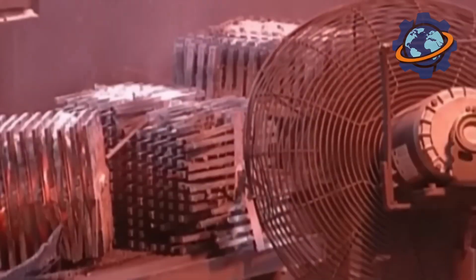Contact with the cold surface of the drum leads to an extremely rapid cooling of the melt at a rate of up to millions of degrees per second. This extremely rapid cooling prevents the formation of large crystal grains and allows for the formation of an amorphous or microcrystalline structure.